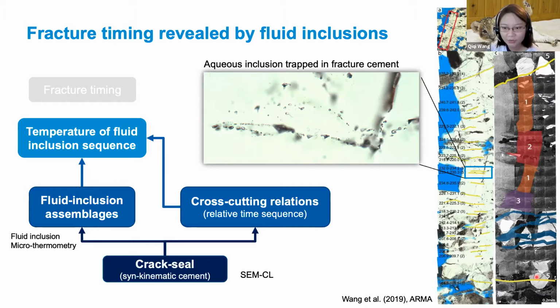And if you pay attention to the width of the zones, they're different, right? So the later formed trails, zones 4 and 5, tend to be wider and they cut through some early cement. By doing this type of mapping, for instance, we see the temperature recorded in zone 1 is lower than in zone 2, and the temperature recorded in zone 2 is lower than zone 3, and in zone 4, if we say the temperature recorded is higher than 1, 2, 3, then we know when the fracture was forming, it was buried deeper, while at the time of zones 1, 2, and 3, but got uplifted during formation of zones 4 and 5.